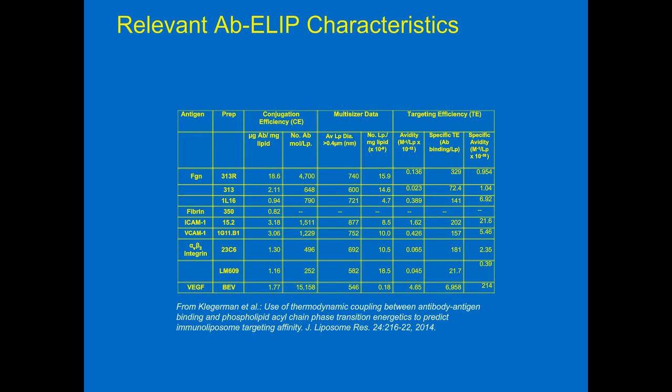So you take that, and that you can enumerate in the multisizer, and then go back and get the distribution for both peaks in your DLS instrument, let's say, and get the number fractions, and then use the same method to determine the number of your nanoparticles. Then you can validate this with something like electron microscopy, one of these gold standard methods. And if it works, then you could still use the multisizer and it'd be of great value.